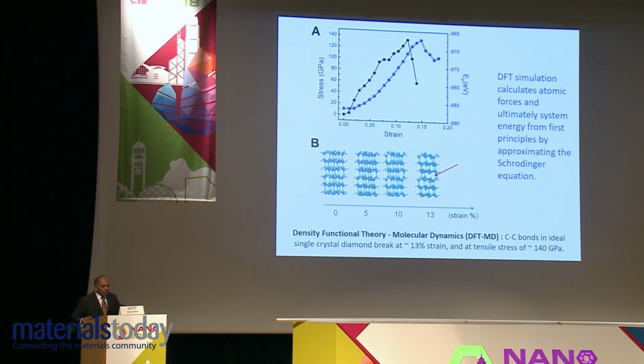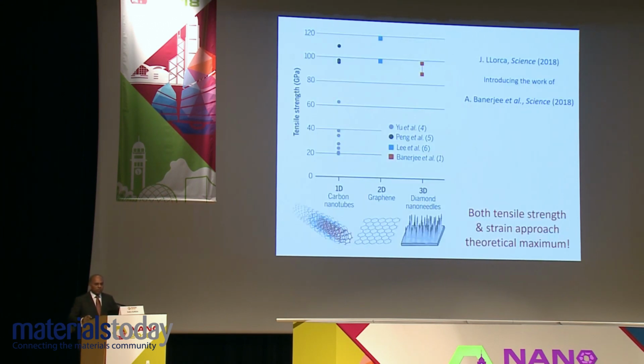We also did density functional theory and molecular dynamics calculations of stress strain curves. What is plotted in black is the stress strain curve from a DFT MD calculation, where we found that the maximum tensile stress is of the order of about 140 GPa, and the tensile strain at which fracture is initiated, at least according to the calculation, can be as high as 13%. And that's the point at which carbon bonds tend to break in this particular simulation.